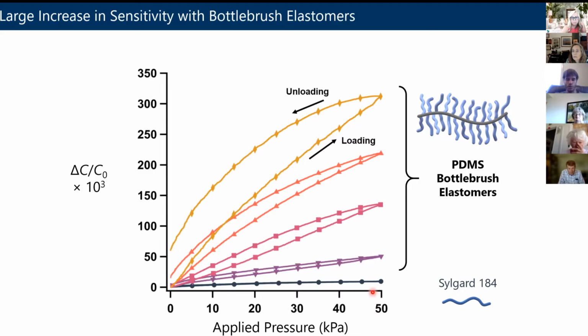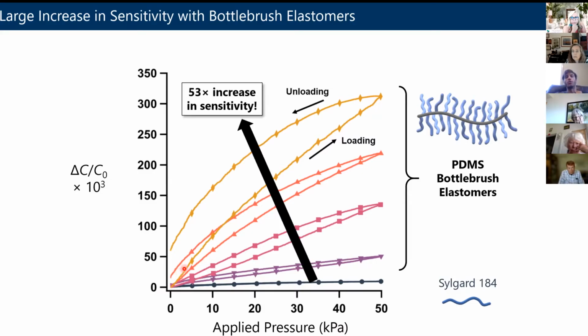This curve, which is really like the baseline in the plot, is your standard linear material. If you put Sylgard 184 in between the electrodes, you can apply pressure in this range and you really don't get a lot of signal out. But when you go to the bottlebrush elastomers, and again, these are 4 different samples that have different lengths of the backbone, different lengths of the side chain, you can see a much bigger increase in the signal when you apply the pressure. And depending on where you calculate it, it can be up to roughly 50 times increase in sensitivity, simply by controlling the polymer architecture.